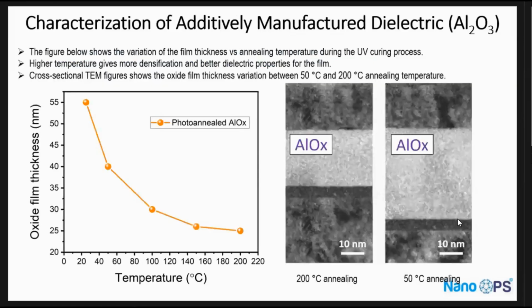And then we tried to look at dielectrics. A lot of times you do densifying of the dielectric to get a very high quality, so actually this was possible as well here. For example, this is without. This is low temperature, by the way. The metal and the dielectric are both sintered at low temperature, 250 or less, which makes it very good for flexible electronics as well. I'm going to show some examples of that. In this case, you can densify it. That means reducing the thickness of the dielectric layer by heating it at 200 degrees, and that gives you a very good quality with the same dielectric constant.